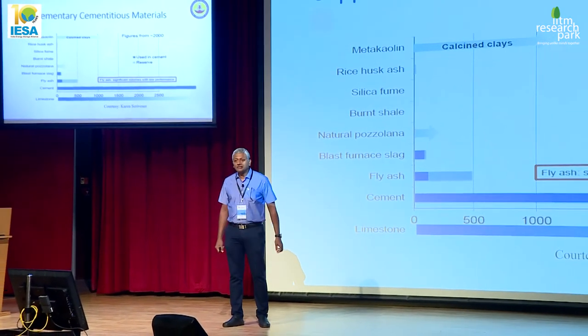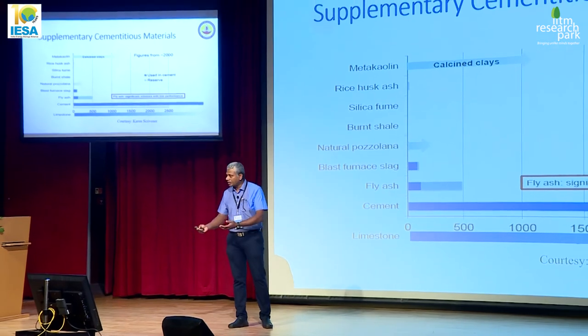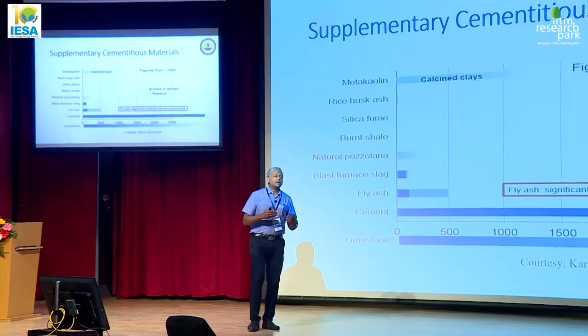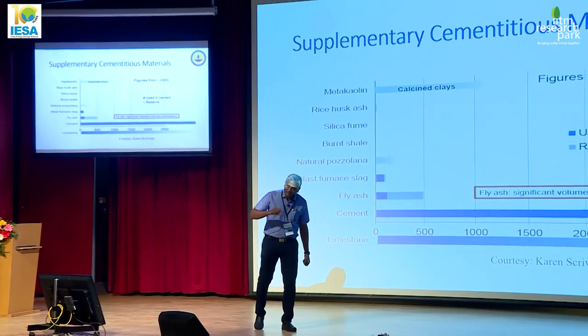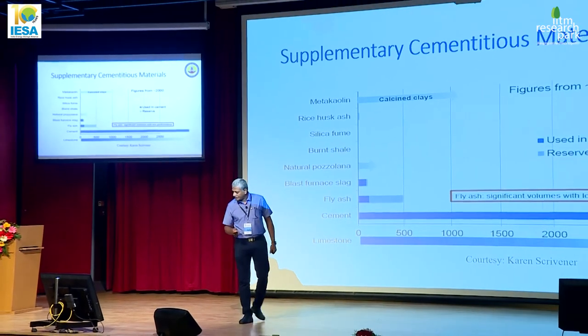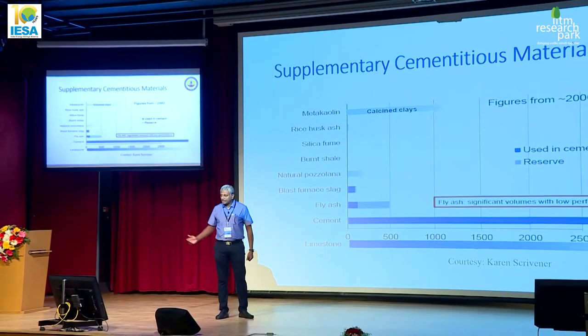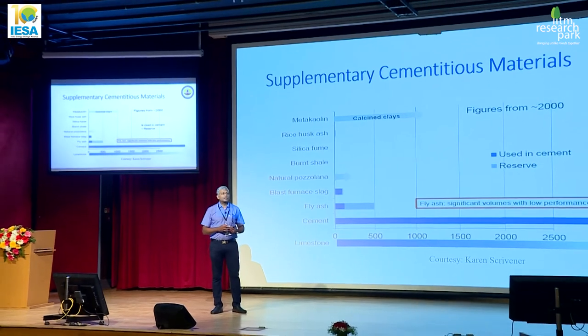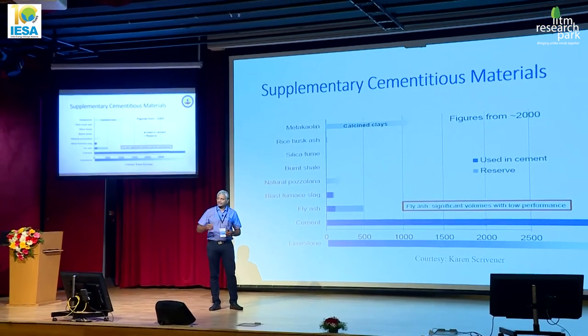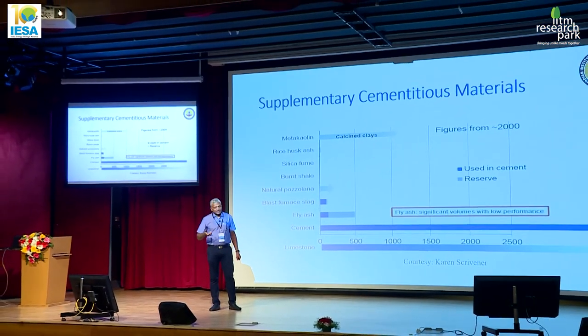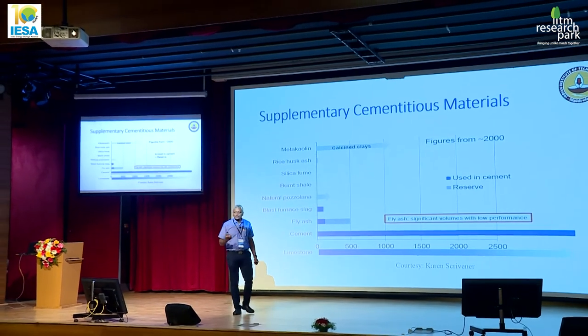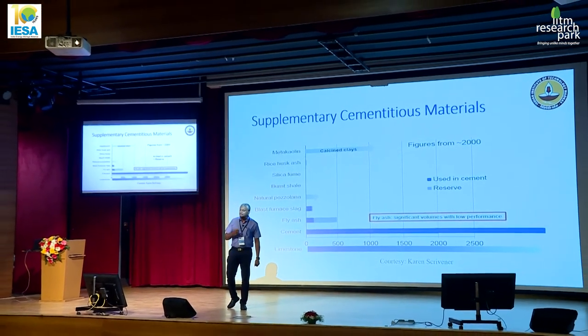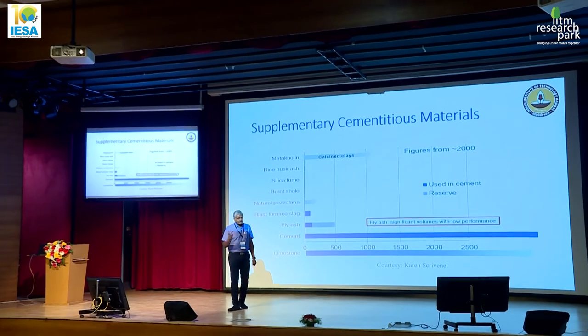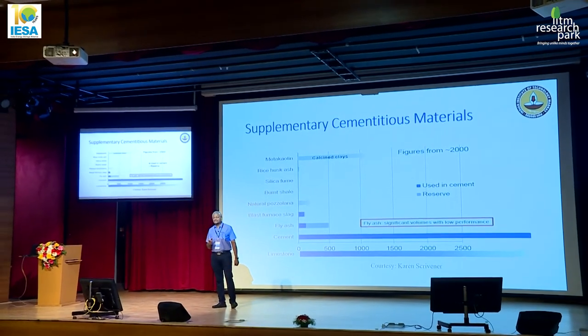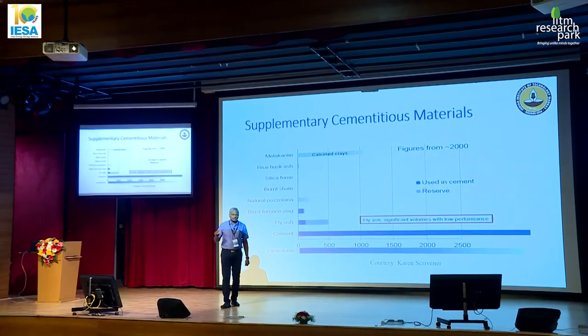In fact, in the market, if you want to buy something to build your house, you can only get what is called Portland pozzolan cement, and that is basically cement mixed with fly ash already, okay? Last one is slag. We do have Tata Steel here. So they know very well about the process of manufacture of steel in the blast furnace. We can extract the slag, quench it, and that becomes a very nice material for cementitious replacement. In fact, it is such a good material that you can replace easily up to 70% of cement with slag,